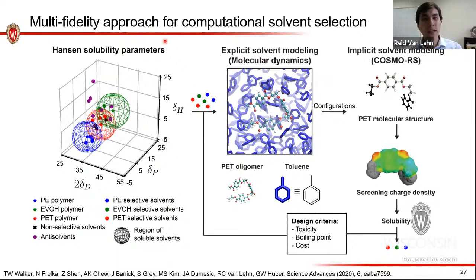These are tabulated experimental parameters to characterize the interactions between a polymer and a solvent. Explicit molecular dynamics simulations, which is essentially like a computational microscope that tells me a lot about how molecules interact at nanometer length scales to drive dissolution. And then a quantum chemical calculation technique called COSMO-RS that I'm not going to talk a lot about, but it basically allows us to screen through solvents very rapidly.